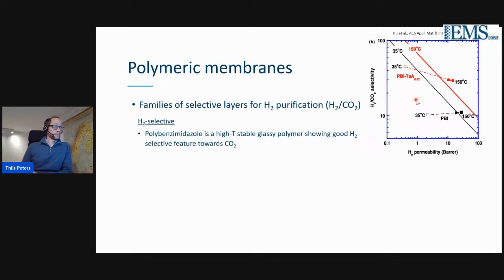And you also have polymeric membranes that are relevant for hydrogen CO2 separations for pre-combustion schemes. So where either the membrane is hydrogen selective, typically made of a material called polybenzimidazole. This is a high temperature stable glassy polymer showing very good hydrogen selective features towards CO2.